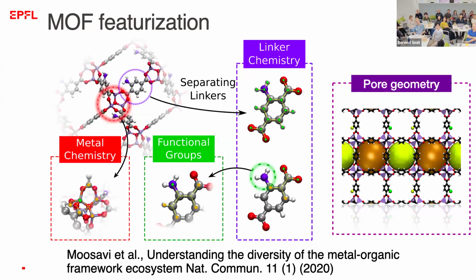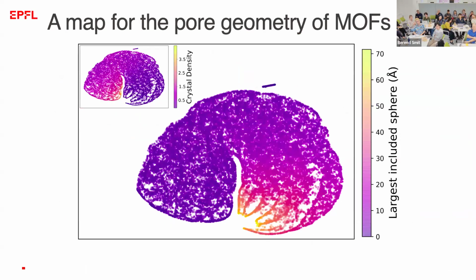So the way we do that is basically we do a featurization of the MOF in terms of metal chemistry, functional groups, linker chemistry, and pore geometry. And then you have a measure of distance, how different these metal organic frameworks are. So here we then collected all the databases, the experimental databases and the databases from hypothetical predicted MOF structures.